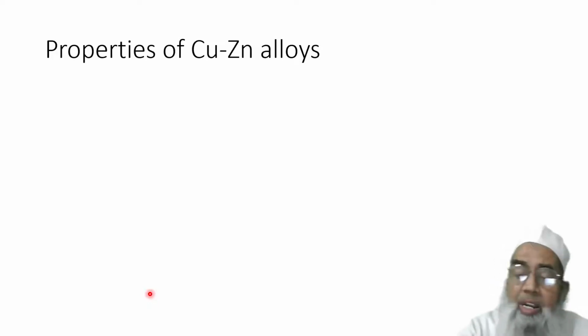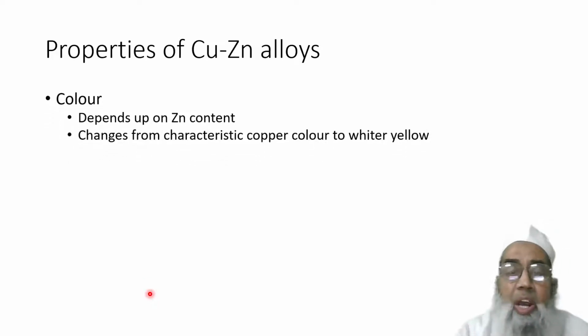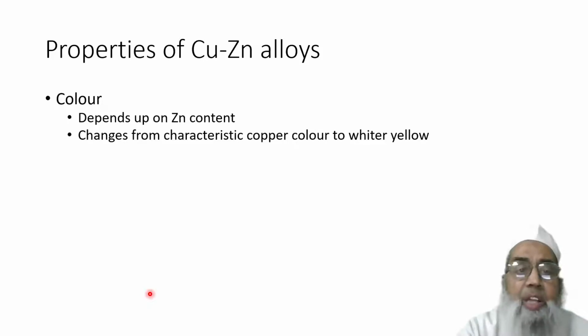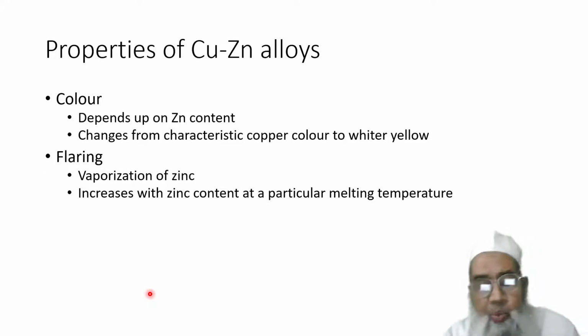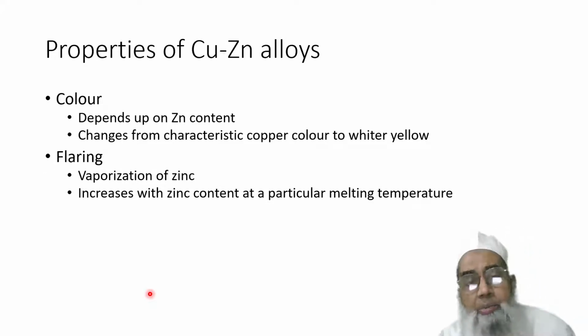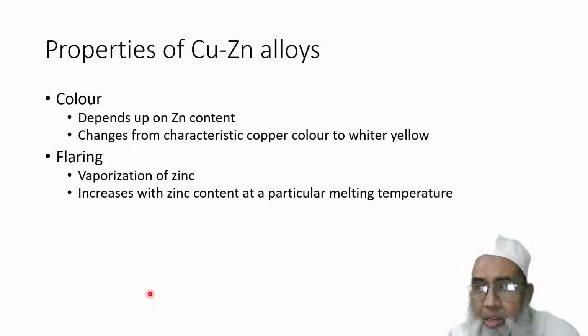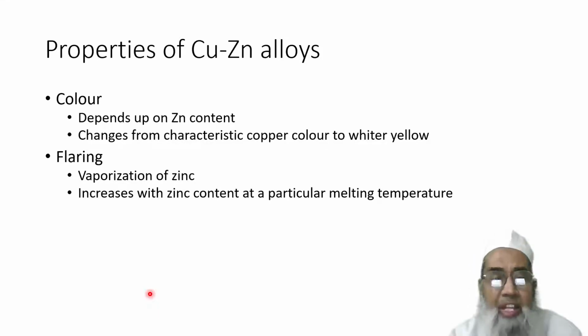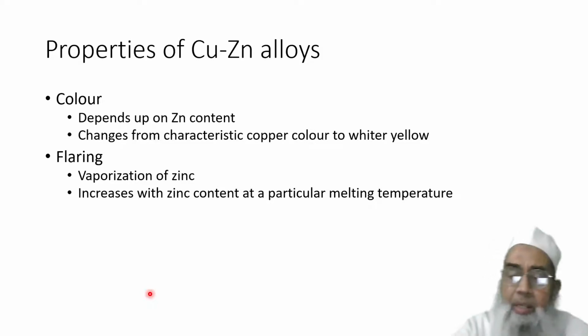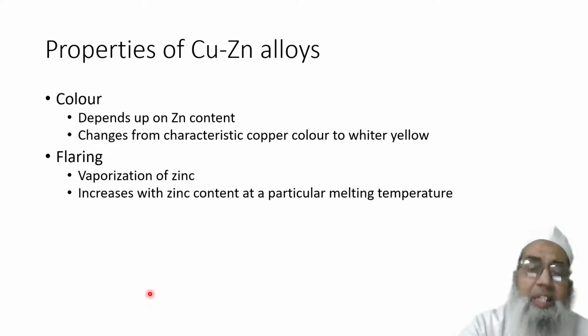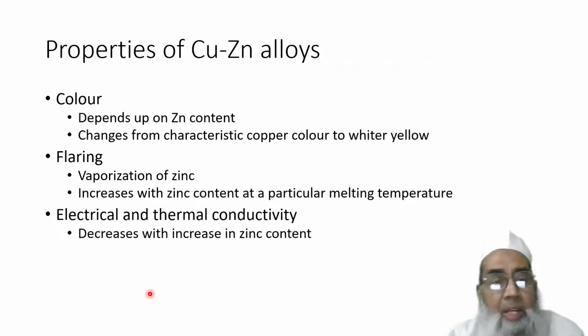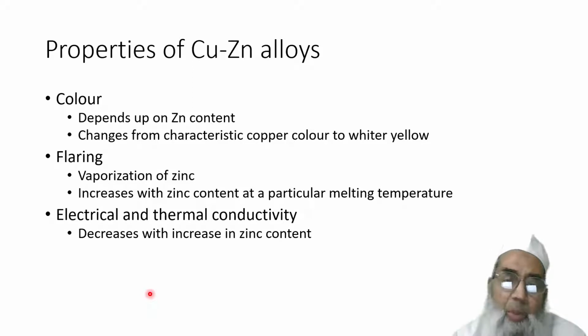Now, similarly, in copper-zinc alloy, the color depends upon the zinc content and changes with the characteristic copper color to whiter yellow. Now there is flaring. When zinc is there, vaporization of zinc takes place. After vaporization, the zinc gives a very glaring white color, which we call flaring. The increase of zinc content at a particular melting temperature increases it. Thermal and electrical conductivity decrease with increase in zinc content.